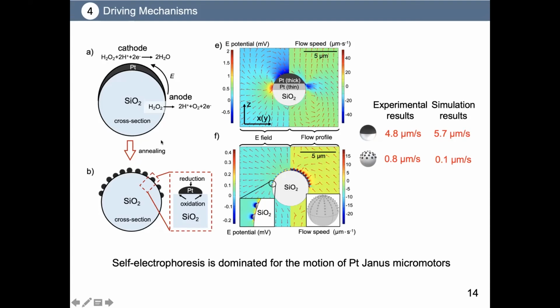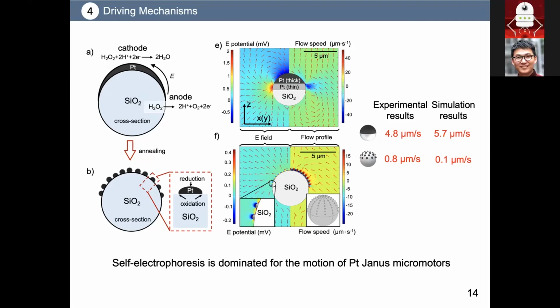After transforming the continuous film into discrete platinum nanoparticles, each of these platinum nanoparticles can be regarded as a nanocell, generating their own electric and flow fields, but these will cancel each other locally, leaving weak global flows around the entire microsphere. So its speed decreases drastically, which is consistent with our experimental results. So we believe that self-electrophoresis is dominant for the motion of platinum Janus micromotors.